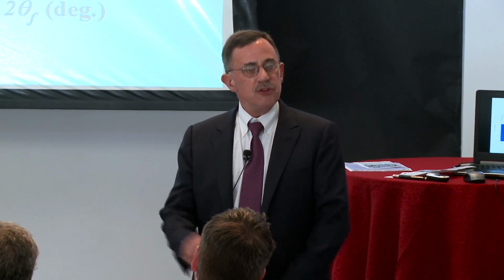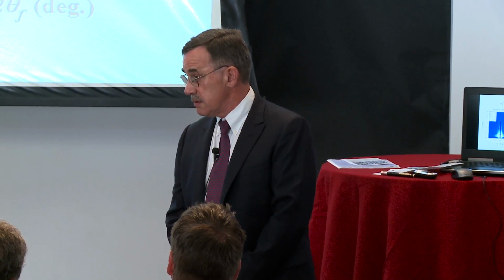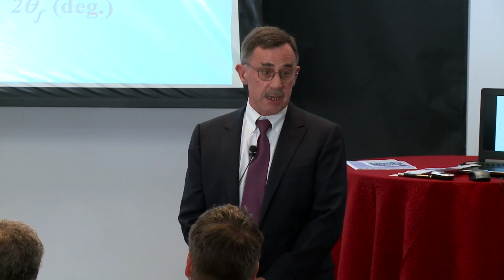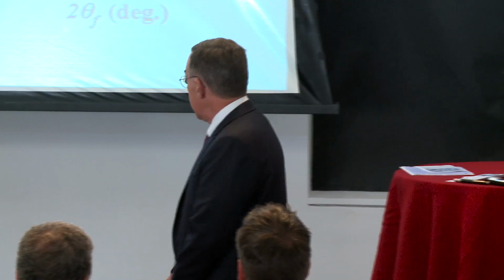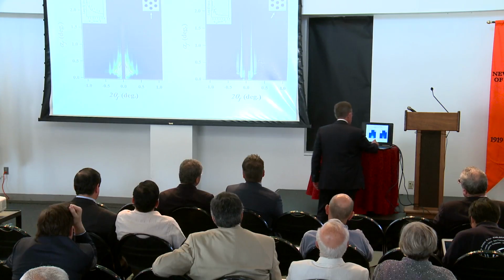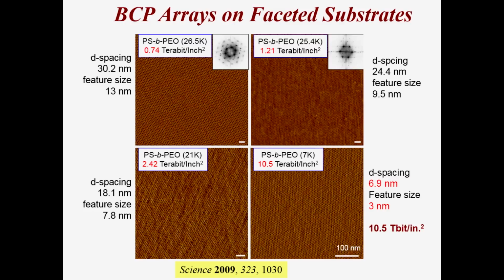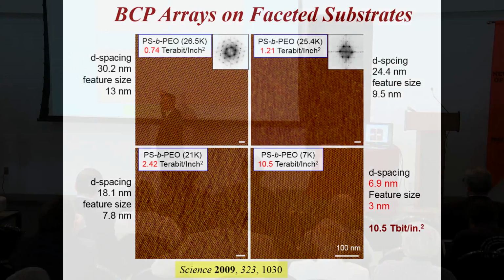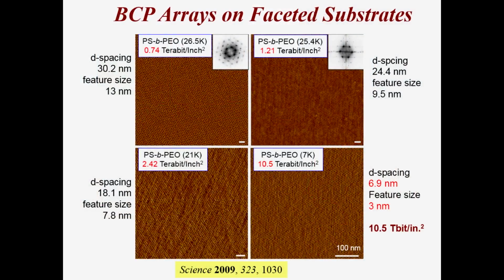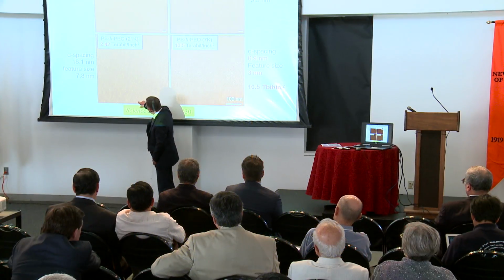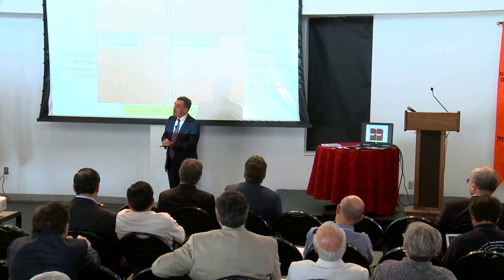However, the rotational order in this is perfect. And it's perfect over very, very large length scales. Right? But there is another order parameter you have to be very concerned about if you want to develop magnetic storage. And that is, if I were to take this substrate, and if I go across the substrate, I can tell you that this rotational orientation, so I know if I go 60 degrees, 60 degrees, 60 degrees, I can look right down a 1-0 plane, or 60 and 30, 0, I can look down a 1-1 plane. However, if I go along this line, if I go from point to point to point to point to point, there's this translational order that's also important. And if there are slight fluctuations, then what will happen is that you lose order.